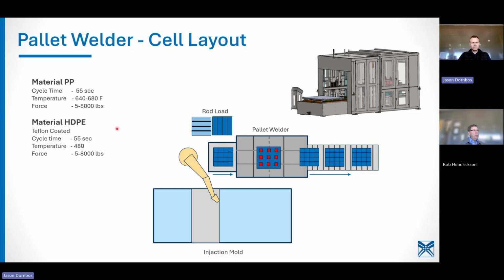When you move to an HDPE, you're going to have a Teflon coated tool, right? Teflon coating means they do wear out the Teflon over time. It makes sense to have other tools there so you can ship that Teflon out to be recoated. Cycle time's about the same. The temperature, though, is going to be significantly less, because that sensitive zone for Teflon is probably in the 500 to 525 range. So you want to keep below that. And the force can be about the same.